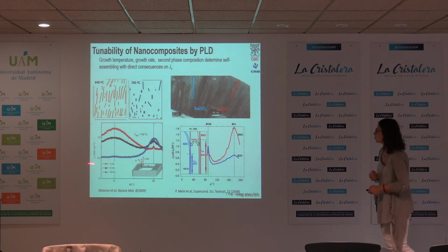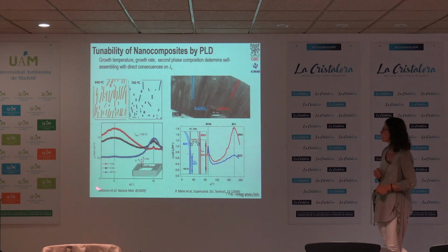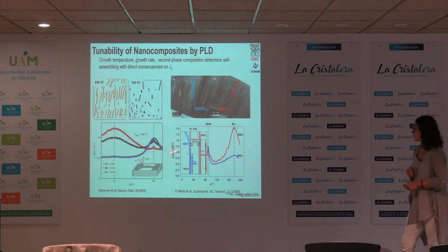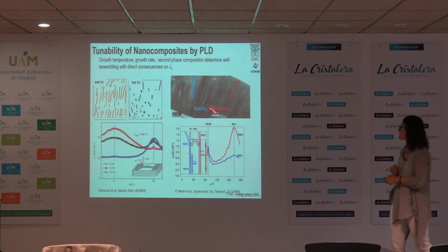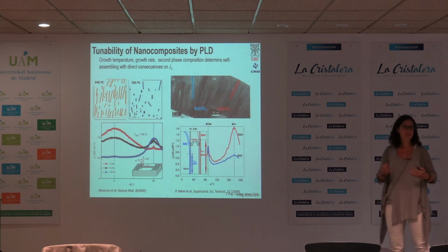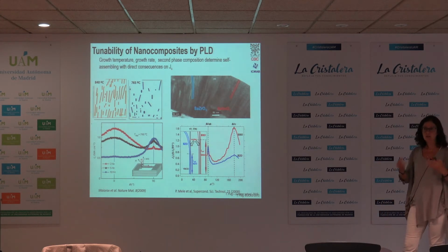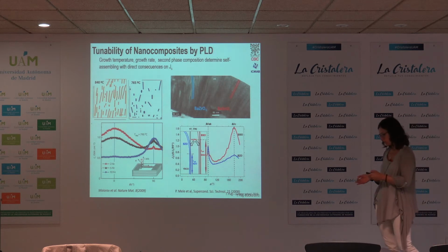And what you see when you measure critical currents, when you go in the same direction as the rod, is that the critical current is extremely increased because vortices are pinned in the rods. This would be without rods, this would be with rods. And you can work with different phases, barium zirconate, barium stannate, phases which really must not be able to react with the YBCO phase.